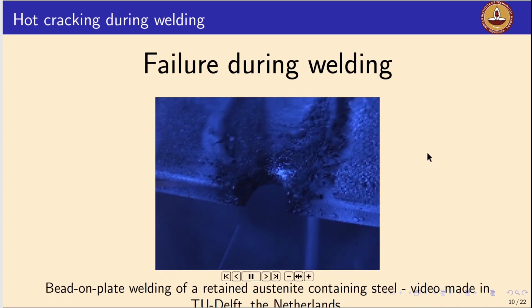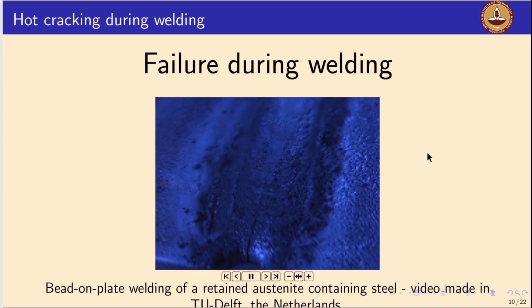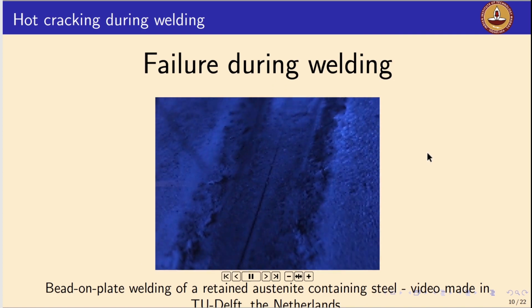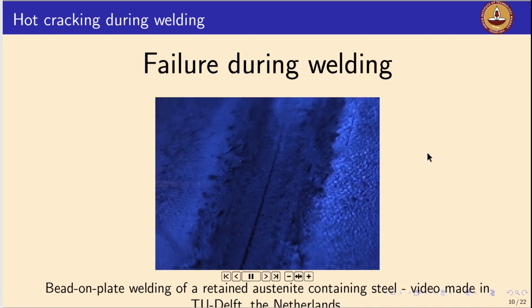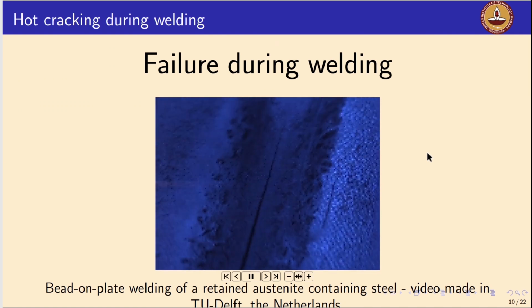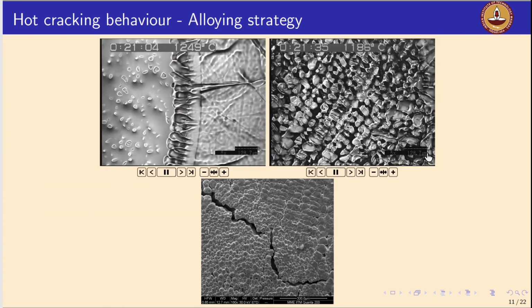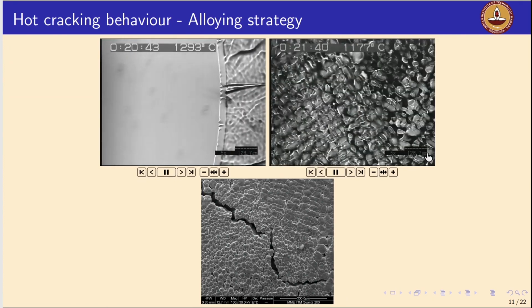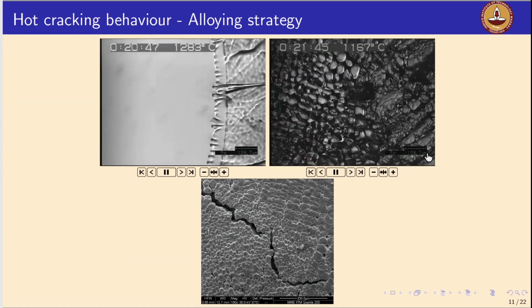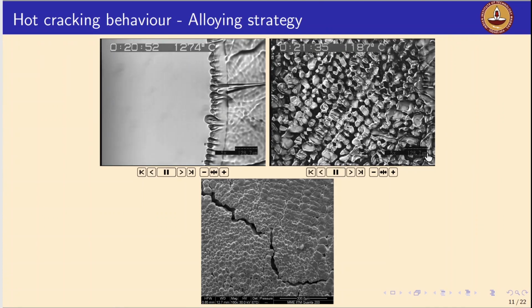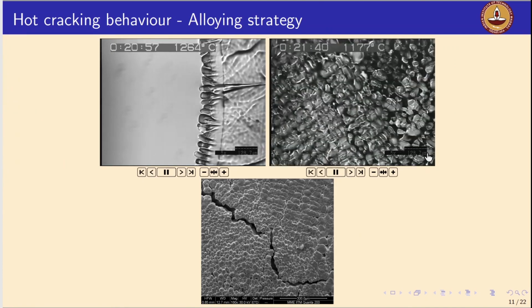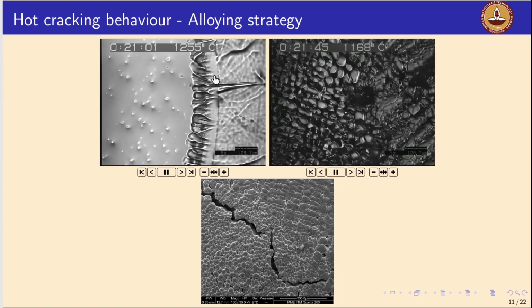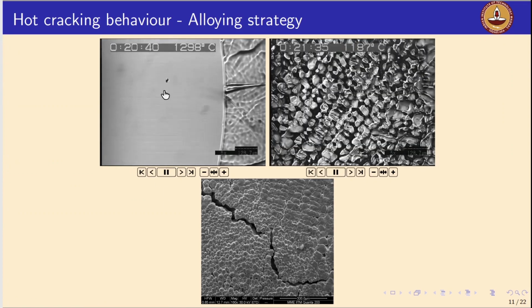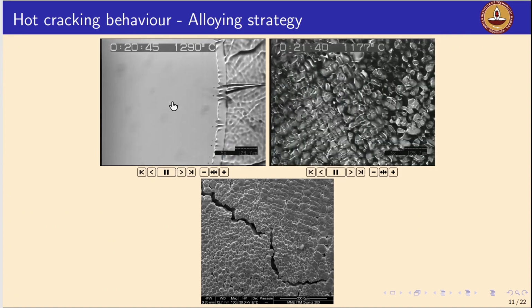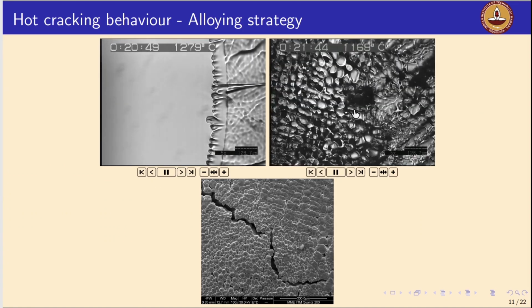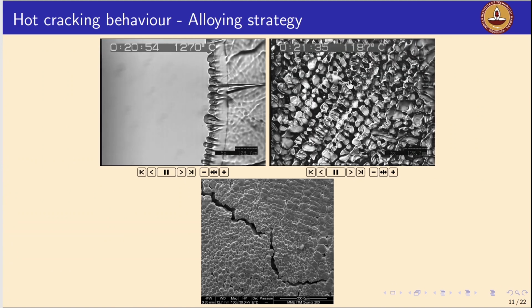So therefore, we have to identify, with the identified chemistries, what compositions can give us welds without any hot cracks, right? So how do we understand the hot cracking susceptibility? We can either look at the in situ microstructure during solidification, right? We can also use laser confocal microscopy, where we can visualize the solidification of the weld pool. This is a very expensive affair, right? We can see the actual solidification of the weld pool and see whether backfilling is happening during solidification, where the liquid can backfill and arrest the crack.